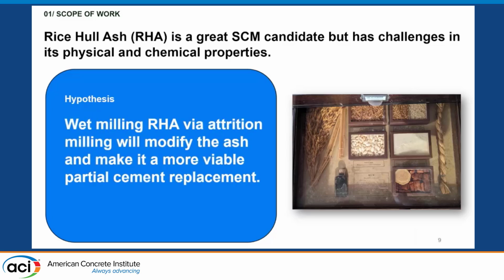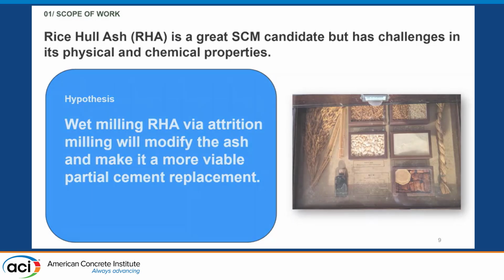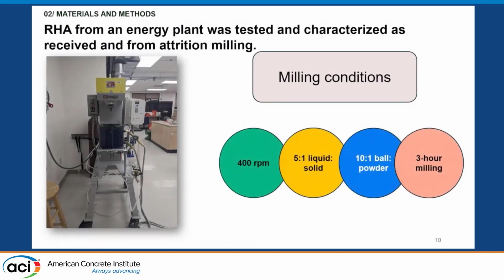And so the hypothesis is that by doing a wet milling process via attrition milling, you can modify the ash and make it more viable as a partial cement replacement. And so the RHA that I have is from an energy plant, and that is another way of using rice hulls that are left after the dehulling process for commercial rice.